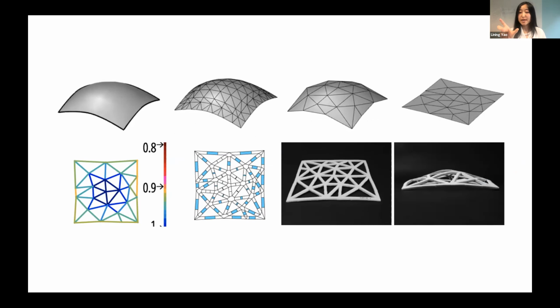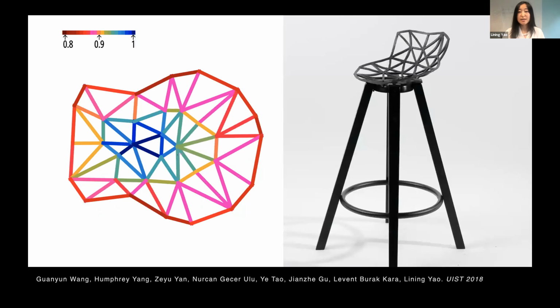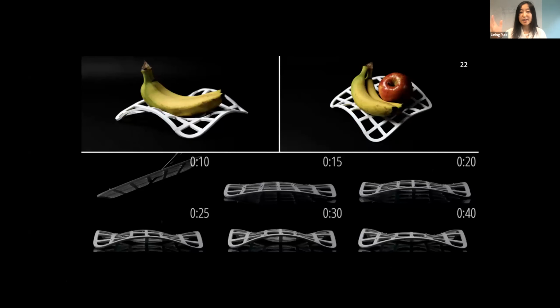And for each beam of the mesh, you can control the local shrinkage ratio per se. And that basically results in a possible non-developable shape that can be computed. So here we made a chair surface and again, printed flat, the color indicates how much it shrinks at each beam. When you place this flat piece into a heated environment, you can get the chair surface.